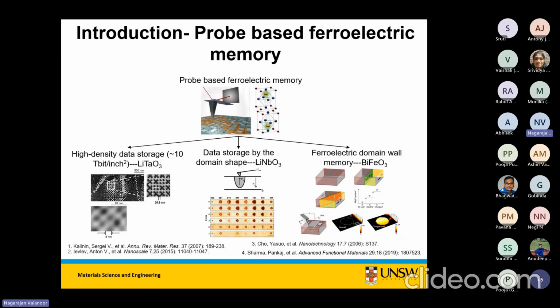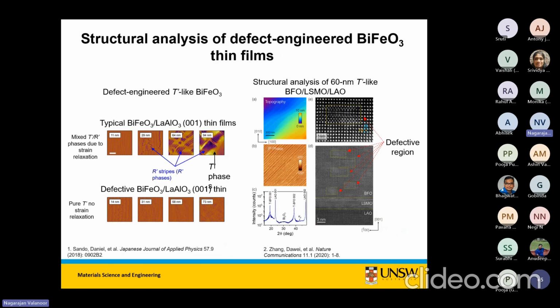I don't know if Bhagwat is here, but I told him that the PLD that we have in our lab, nobody else can do that, because this PLD gives us amazingly defective films. But we exploited this. It's again the PLD with the long throw distance. And what we find is that because the growth is so slow and bismuth is constantly being lost, we have to play around with the target chemistry.